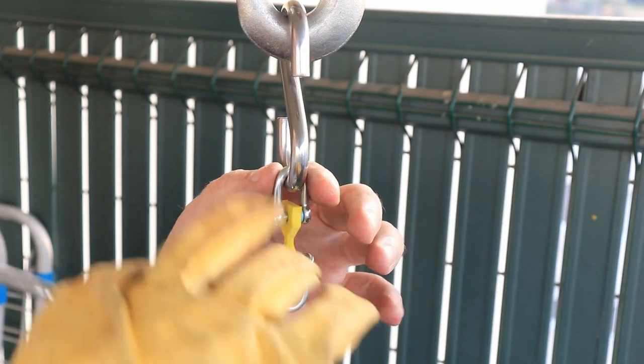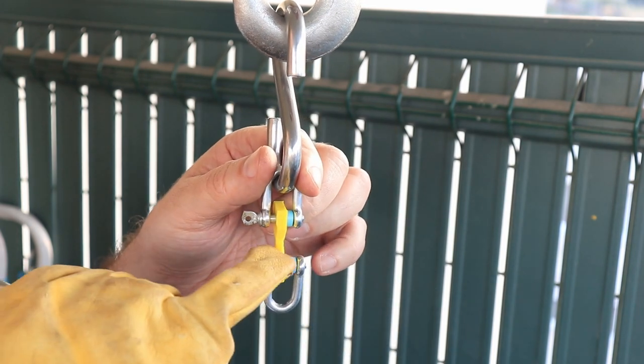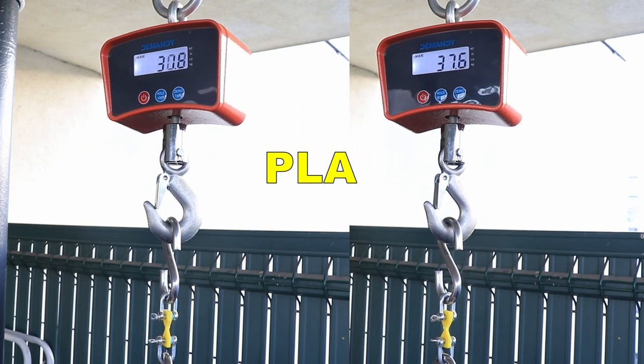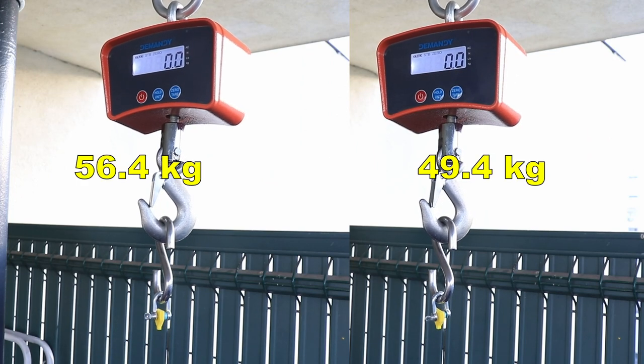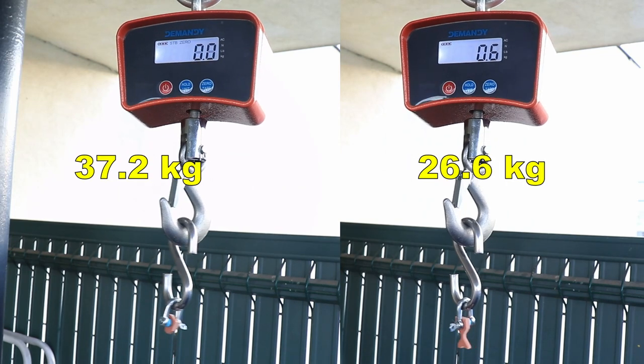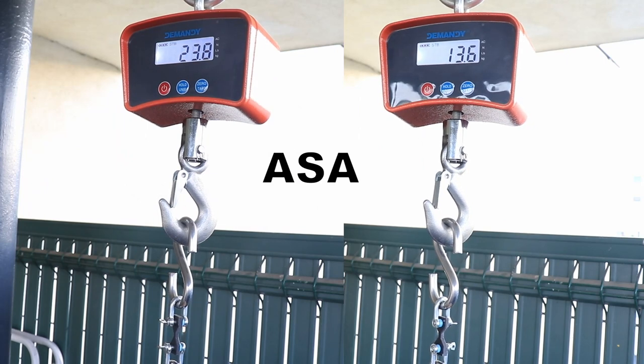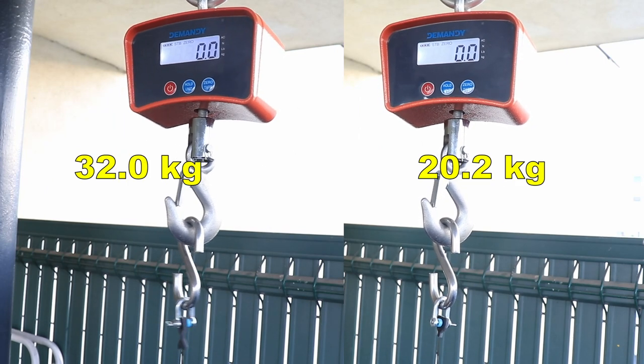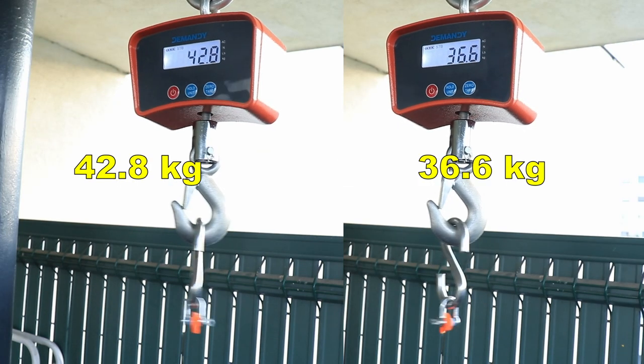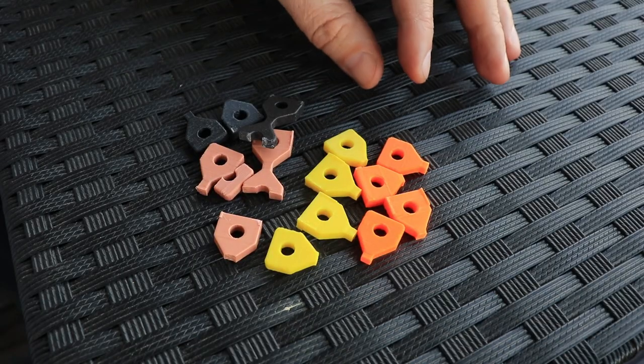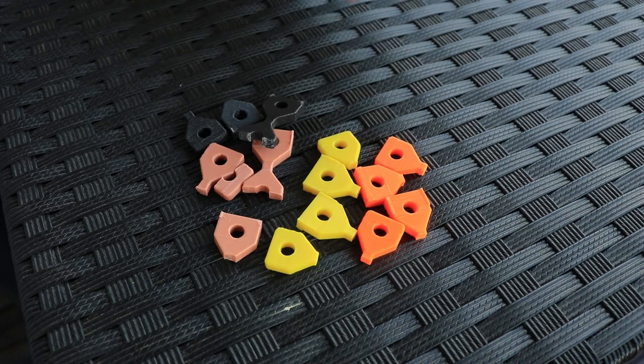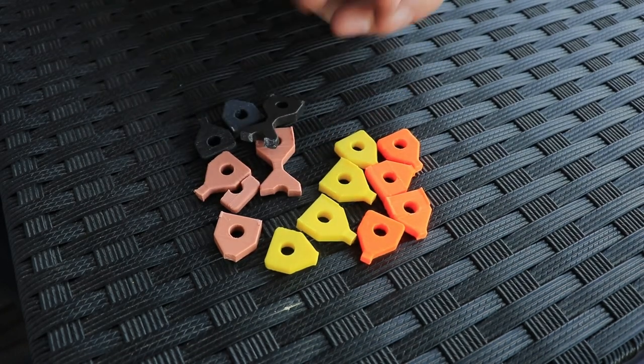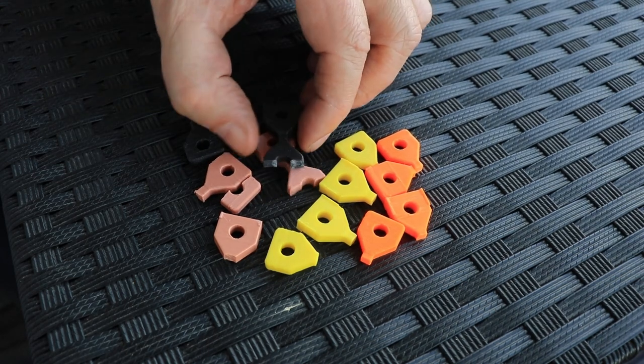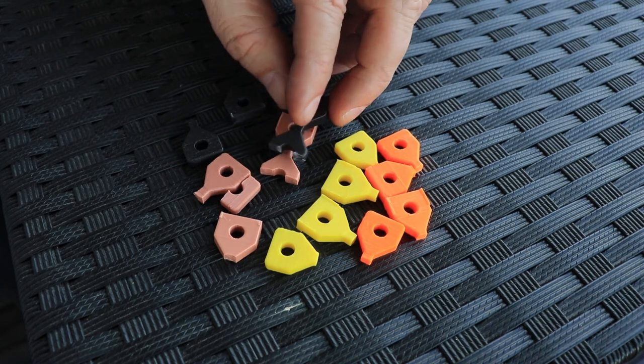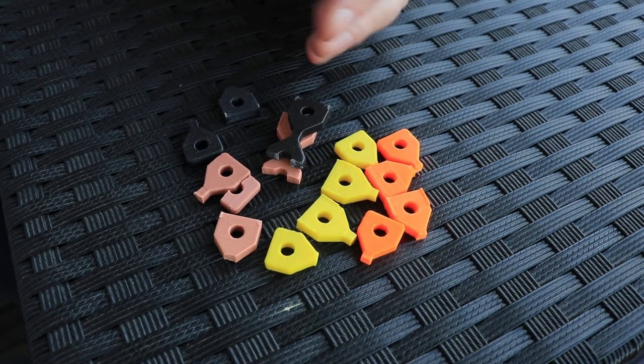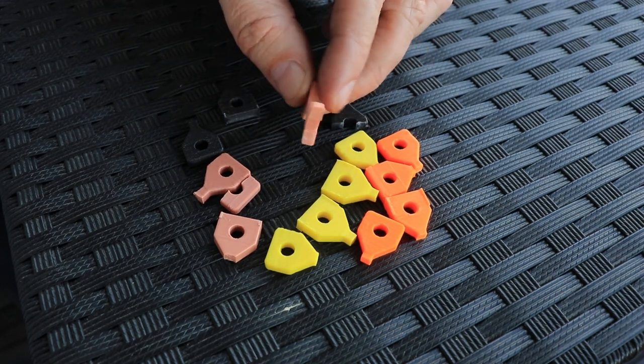And it's time for the layer adhesion test. This test object is printed in vertical position and the smallest cross-section area is 4x4 mm. I'm not sure what to tell you, so I just feel that PLA and PC blend is in one piece, that constant layer adhesion I could feel. But I couldn't say that for the ASA and PETG, and as you can see, even one of the test specimens didn't even break in the correct position. And I'm not sure what is this inconsistent layer adhesion. I could even feel that this one broke on the lower load.